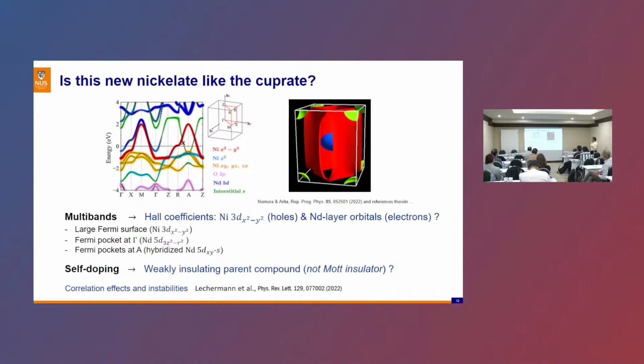All right, so I just try to relate a little bit with what people have predicted from DFT, and Carsten has discussed this a lot. But as we can see here, this is without correlations, of course, and we have heard about correlations, and maybe Frank is going to talk about more today. We can see at the Fermi level it is very busy with orbitals, occupied by combinations between nickel 3d and the 5d hybridized state. The Fermi surface is dominantly having this 3d x square minus y square. And then at the A point, you can see this pocket of hybridized Nd 5d xy and probably interstitial s state. As well as at the center, the gamma point, you also have this Ni 3d 3z square minus r square orbital.